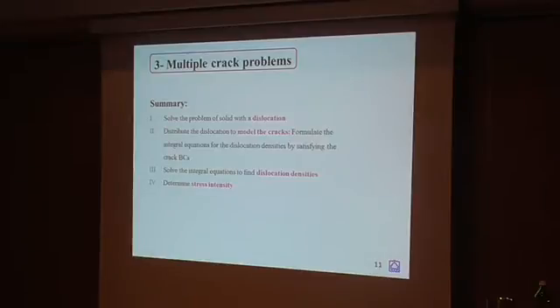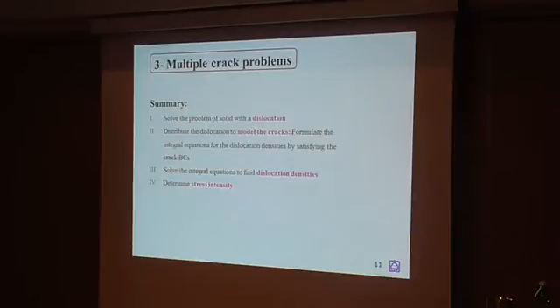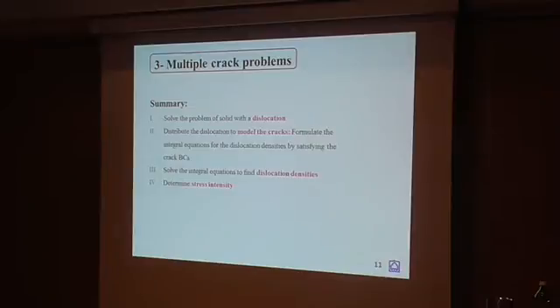Summary: First, we solve the problem of a solid with a dislocation as a Green's function solution. Next, we distribute the dislocations to model the cracks and form the integral equation for dislocation density as the unknown, satisfying the crack boundary conditions. Then we solve the integral equation for dislocation density using a collocation method. Finally, after defining the dislocation density function, we determine the stress intensity factor of the cracks.